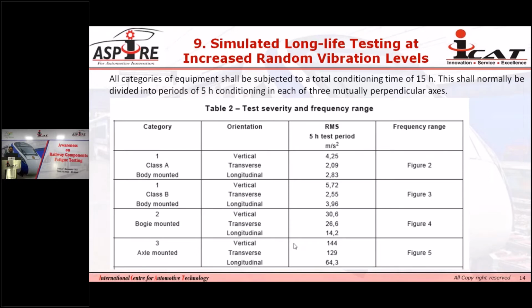For category 2 and category 3, this order is different for the transverse and longitudinal direction. For category 2, you will find comparatively higher acceleration level along the transverse direction compared to the longitudinal direction. Similarly, in category 3, higher RMS acceleration level in the transverse direction compared to the longitudinal direction, because of the orientation of test samples mounted at this position.